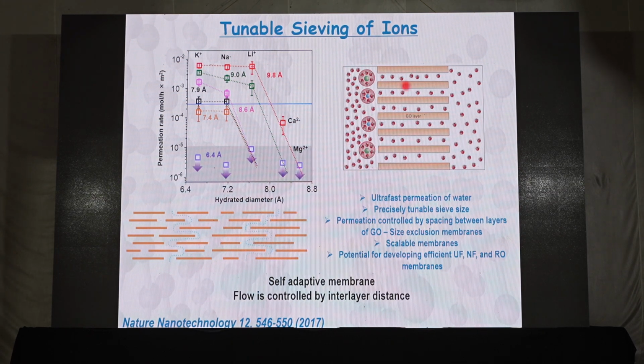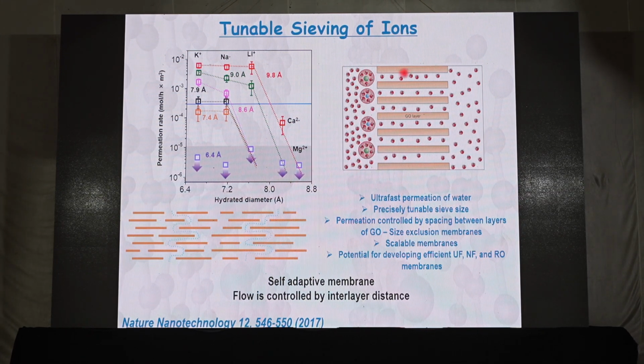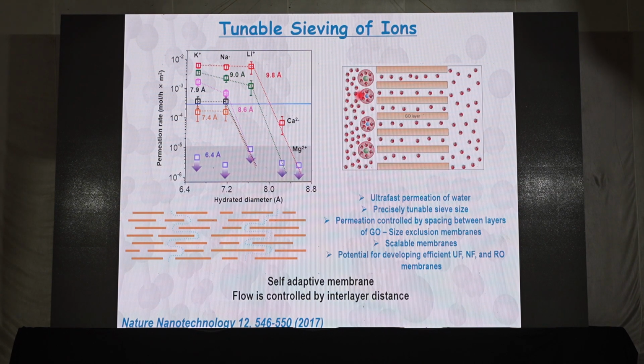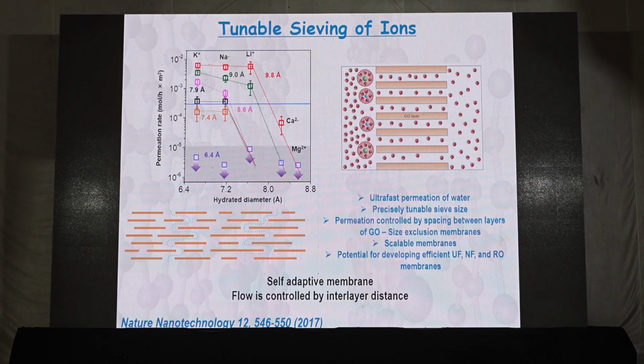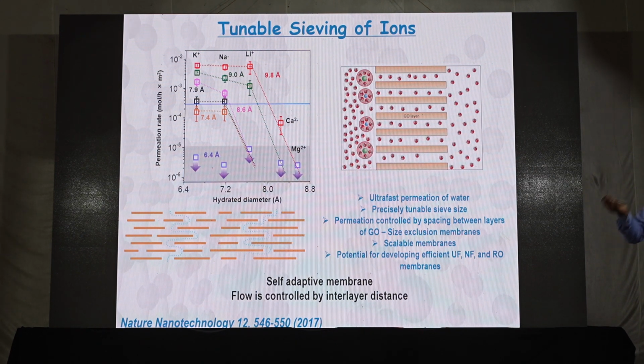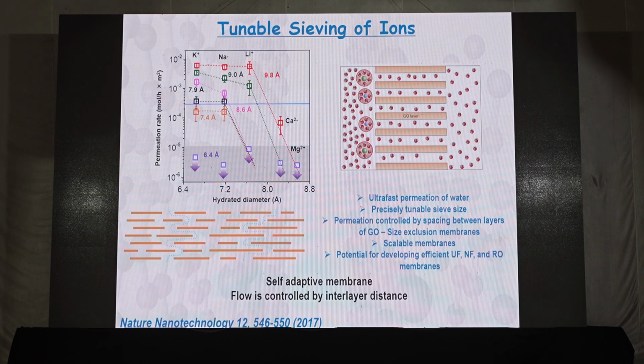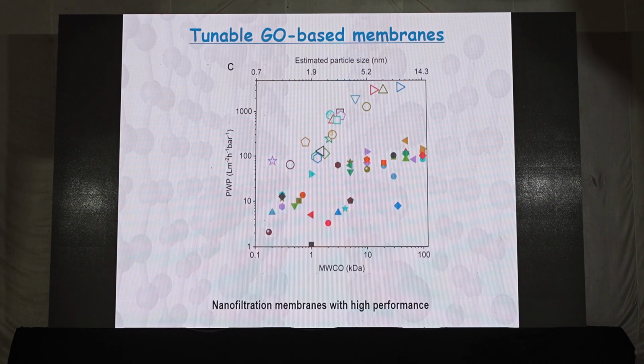You have different channels. These channels only let water pass through, but the sodium, when you put sodium chloride in water, the sodium will get solvated, we call hydrated. A couple of layers of water go around the sodium atom to get hydration, and that hydrated ball will not go inside the channel, and you get selectivity. So this is a very, very simple picture.